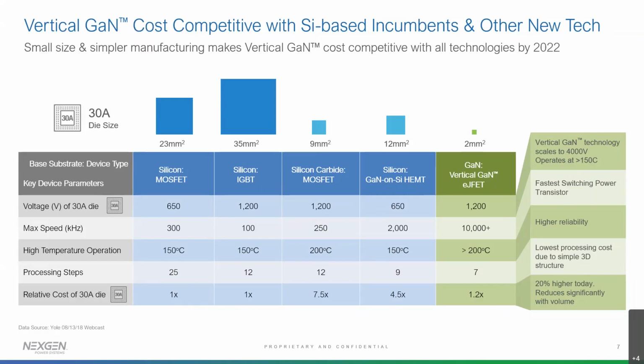And this is a property which is only shared with silicon carbide, but at a much larger die size. Silicon IGBTs, of course, can carry this breakdown voltage as well, but at an even larger die size. So that is one of the major differentiators. And because we have this small die size, the capacitances in our device are very small, and this allows us to address very high switching frequencies. The switching frequencies can go up to 10 megahertz and more, which also sets us apart from the lateral GaN on silicon transistors. And we have a distinct advantage here, which we also show in one of the further slides.